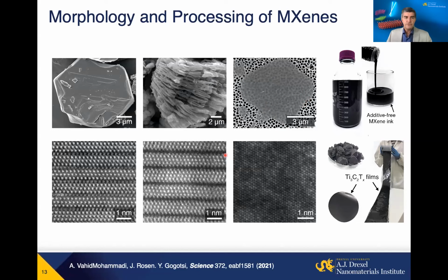What is important is that because of this surface termination, this material is hydrophilic. So we get a material which on one hand is a metal. Electrons of this transition metal provide metallic conductivity, so true metals with high density of states at the Fermi level and metallic properties, but they're water soluble without any surfactants. So we can get a stable colloidal solution in water. Zeta potential is typically below minus 30 millivolts, so they form a stable colloidal solution, from which we can either make ink, or we can use a highly concentrated slurry to make films directly. And this is about 50 grams of powder you can see here in a dish.